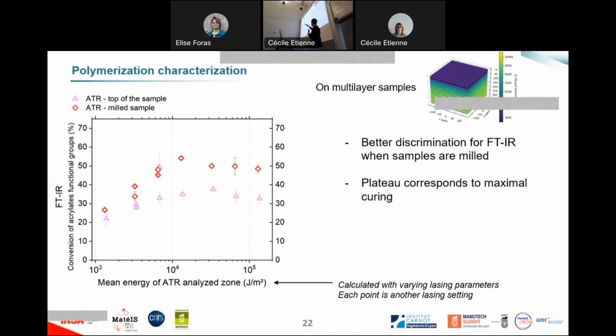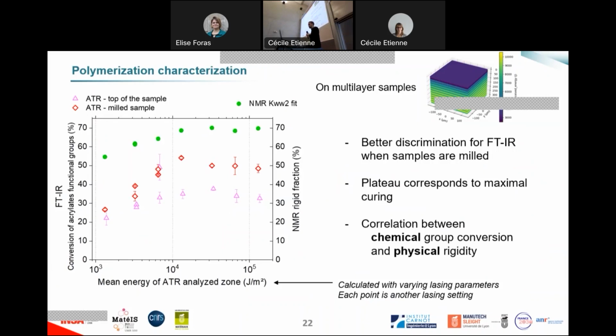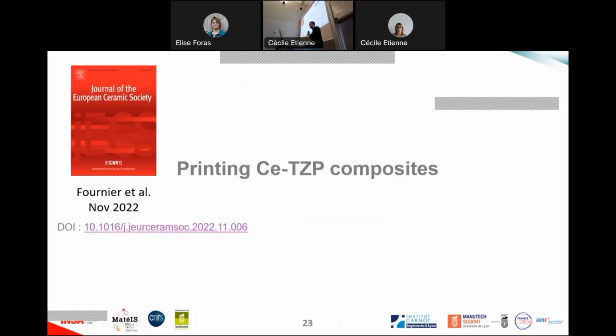So this technique permits us to have more reliable results and to locate well how much energy we need to provide for having good polymerization. So we can locate the plateau. And also here, the first results for NMR gave us the same trend about the energy. So it would be a very nice thing to have another way to characterize polymerization, but with physical rigidity instead of group conversion, to provide more understanding on the way it polymerizes.